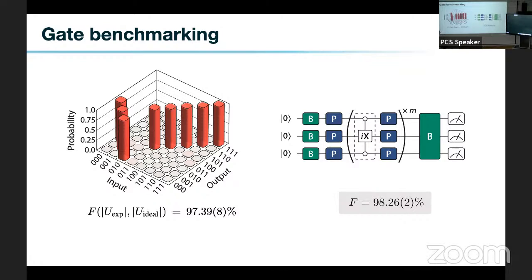Currently it's not a big contributor, but there are 2 points. The first one is because the system temperature is not absolutely zero, so there is a fluctuation due to the quasi-particle population. And additionally, the radiation comes from the outside, which also breaks the Cooper pair, so it also reduces the coherence time. So there are several mechanisms in the decoherence. If I understand correctly, you mentioned the thermal fluctuation and the radiation. Yes. The main source is the dielectric loss currently. You mean that there is some energy exchange with the dielectric? Yeah, that means the exchange with the dielectric surface, the silicon surface or sapphire surface.